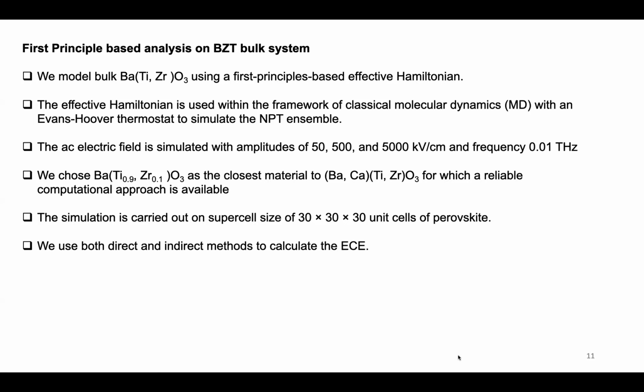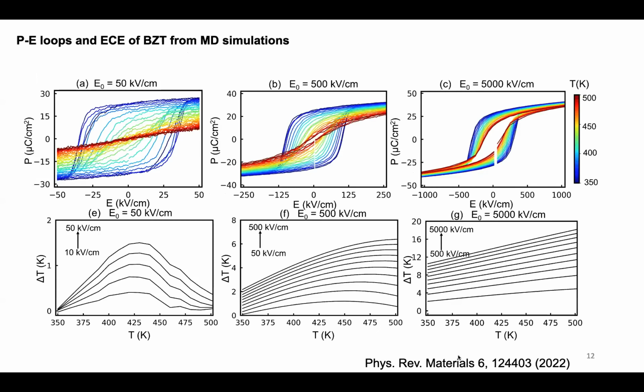Here I will show only three important amplitudes of the fields, and it's the AC field, on a supercell of 30 by 30 by 30. We have done both the direct and indirect methods, but I will show the results of only the indirect one, which can be linked to the experimental results. And yes, these are the P loops from the MD simulations. This is for 50 kV per centimeter. You can see there's a clear transition from ferro to para. And the color bar is the temperature range, 350 to 500.